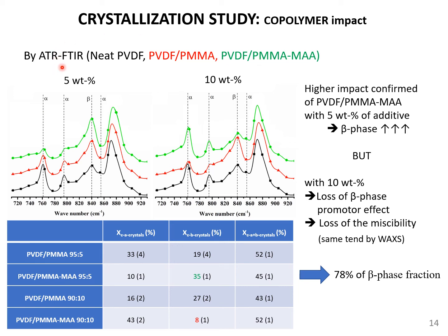We report the values at 5 and 10%, and the relative values obtained based on this graph are reported in this table, particularly the alpha phase content and the beta phase content. You can see at 5%, a slight increase of more or less 80% of the beta phase when you pass from the PMMA to the copolymer. So again you have a positive effect.